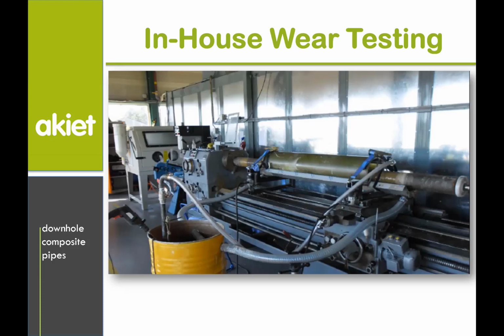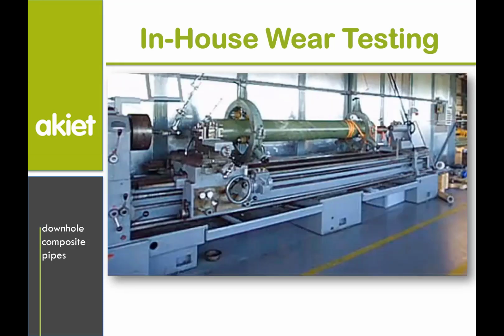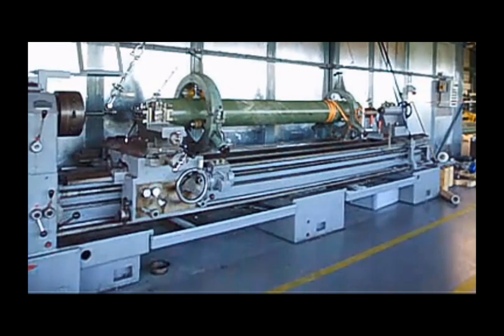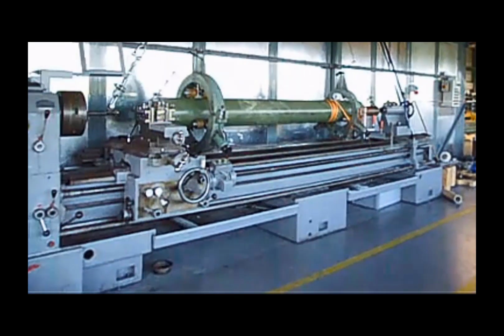Another test that we did was a very similar application. What happens when you drill through the casing and the banging of the tool joints against the inside? So this is a machine where there's an installation which drops the tool joint on the inside of the casing, and we've run that for hours and hours on end, with mud in the system. The result was the same. There's no delamination, there's no wear, and the pipe body actually holds up extremely well.